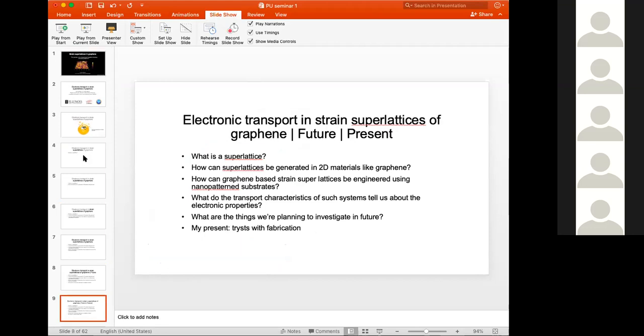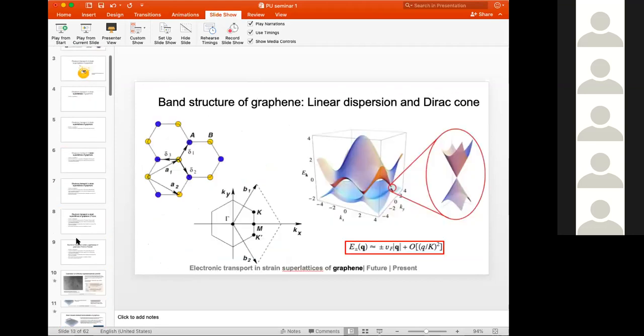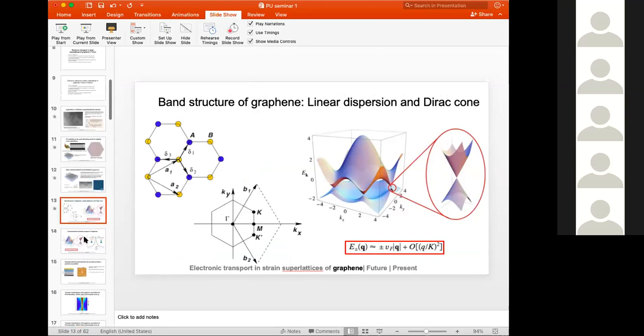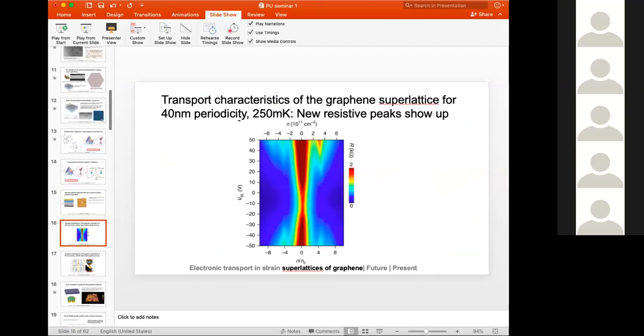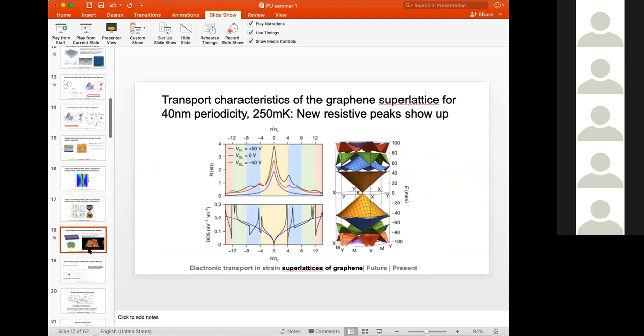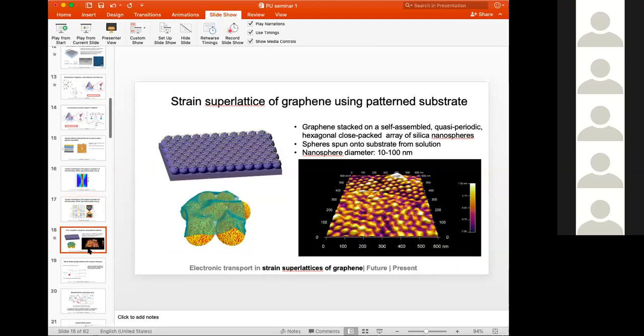One other question. In some slide I have seen that the nanosphere size varies from 10 to 100 nanometers. So how do you make sure that you are getting a superlattice that has the same dimension all around? In any specific sample, you have nanospheres of just a certain diameter. Either we are using 10 nanometers, 20 nanometers, or so on. These are different nanospheres that you can get. It is not varying within the same sample. No, because that wouldn't give you this close-packed structure.